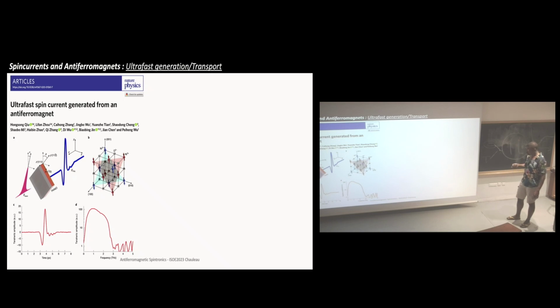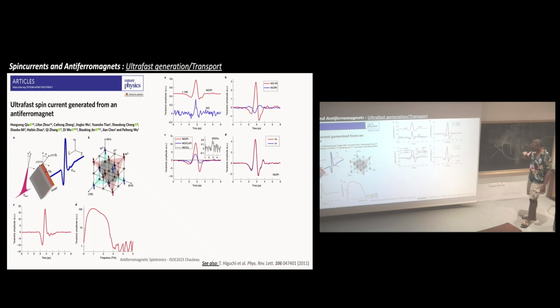Okay, so it's kind of important. So knowing this, those people, what have they done? They have taken an NiO sample, an NiO/platinum sample, they have shone a femtosecond pulse, and they have measured if there is terahertz light going through. Okay, and they say if there is some kind of proof of ultrafast spin current. So this is what they have done. And this is what they have. So this is very nice.